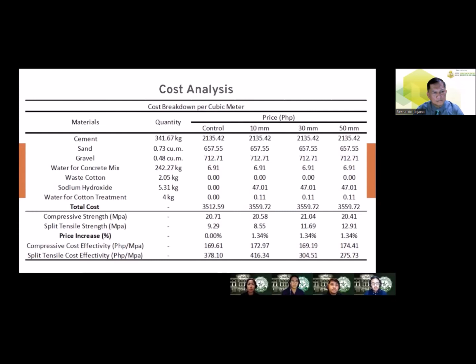So looking at the total cost, the addition of the treated cotton fibers in the mix results in a 1.34% price increase, that is 47.12 pesos, compared to a control sample. And having done the cost effectivity, it was observed for compressive strength that 30 mm is the most cost effective, having it to be lower than the control. And in terms of the split tensile strength, 30 mm and 50 mm were found to be the most cost effective, having it to be lower than the control.